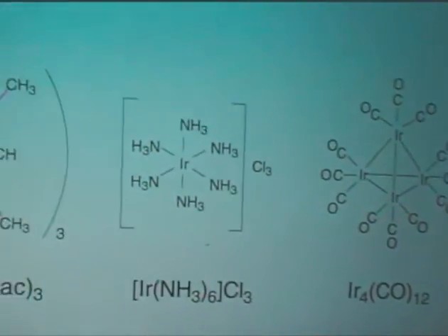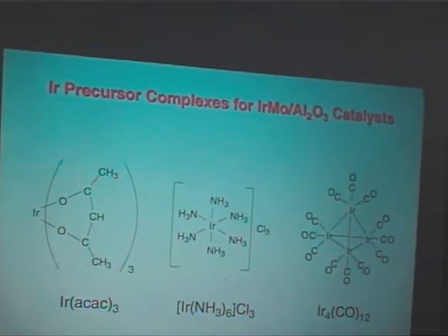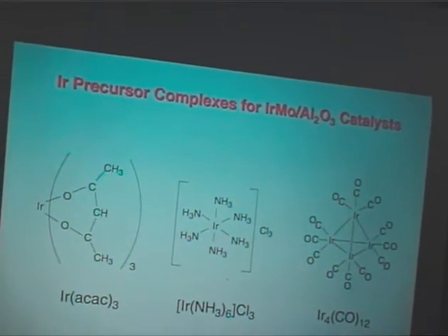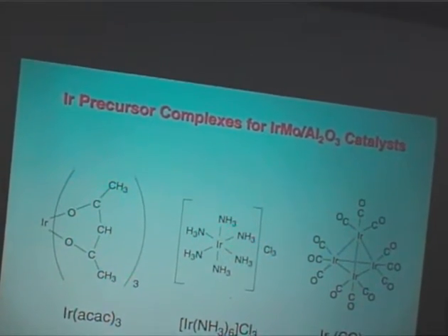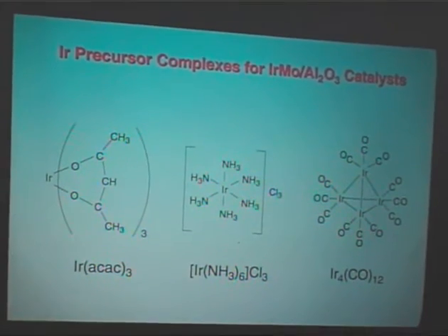We have on the left tris-acetyl-acetonato iridium. This complex is very soluble in most organic media, but it is insoluble in water, and it is rather stable towards higher temperatures. It is reported to decompose at 290 degrees C.